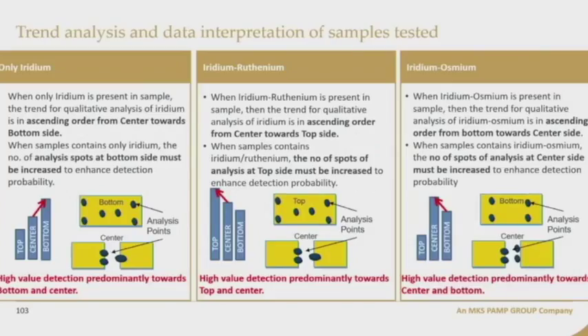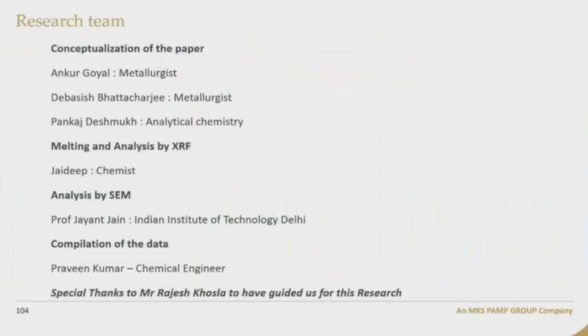So what do we conclude? We conclude that in case of iridium, high value detection is predominantly towards bottom and center. So analysis spots should be more at the bottom side and a few at the center. In case of iridium ruthenium system, there's high value detection towards top and center. Analysis points should be more at the top. And in case of iridium osmium, more at the center.